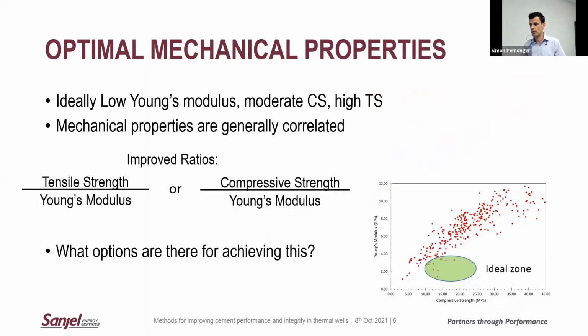So, what sort of properties are ideal? Really you want to have a low Young's modulus, a high degree of flexibility, moderate compressive strength, and as high a tensile strength as possible. But the real difficulty here is that all these mechanical properties are very, very highly correlated and related to each other. If you have a look at the scatter plot that I've got there, this is a couple hundred tests that we've done in the lab here. You can see a strong correlation between your Young's modulus and your compressive strength. And if you pick the other properties, you would see a similar correlation. So it's very, very difficult with conventional cement designs to lower the Young's modulus without also sacrificing the compressive strength or the tensile strength.